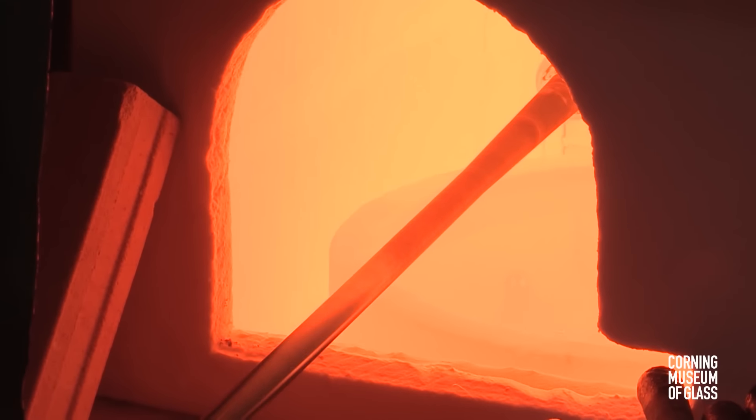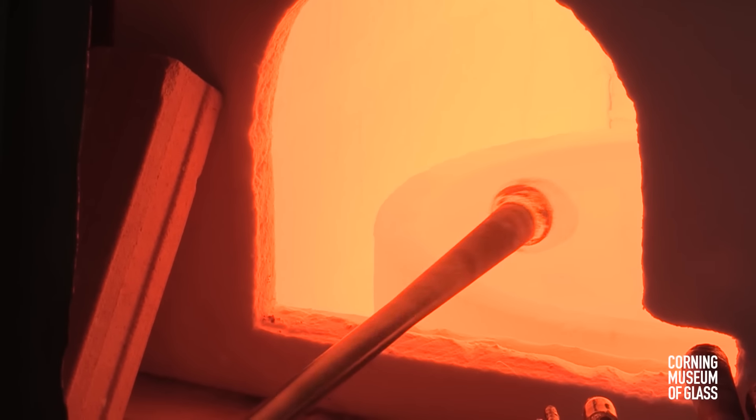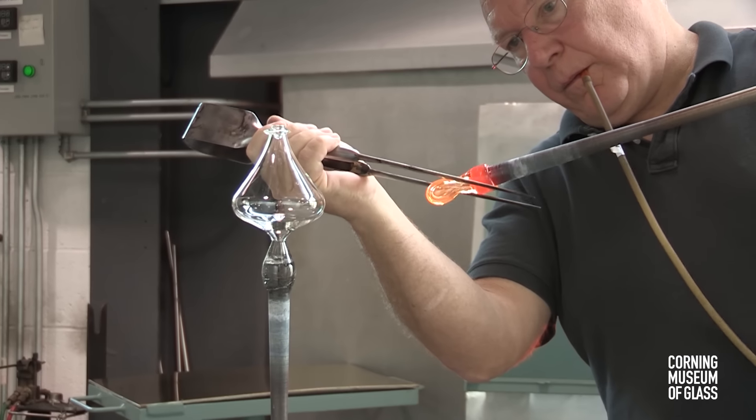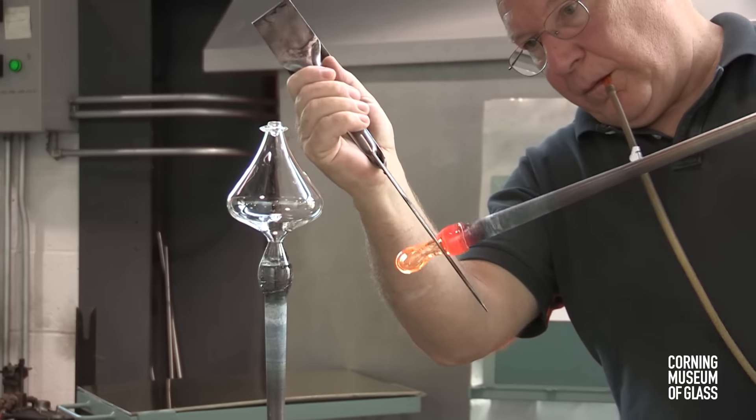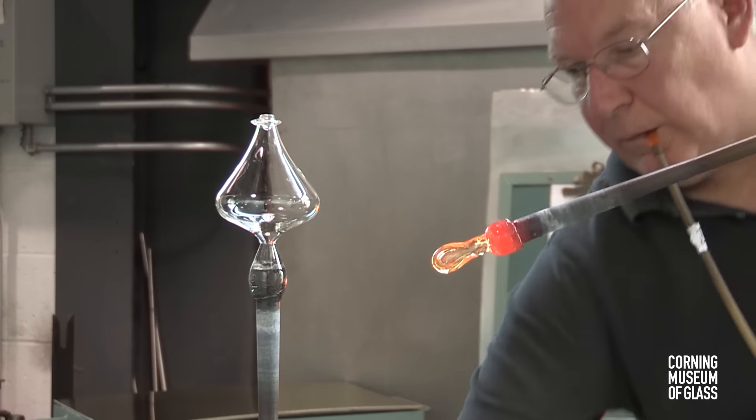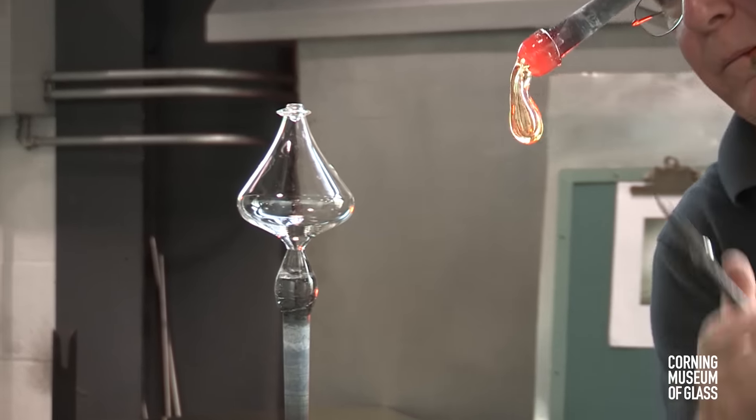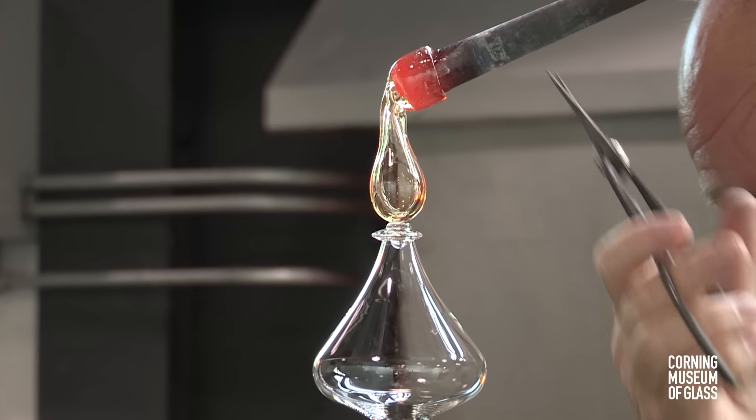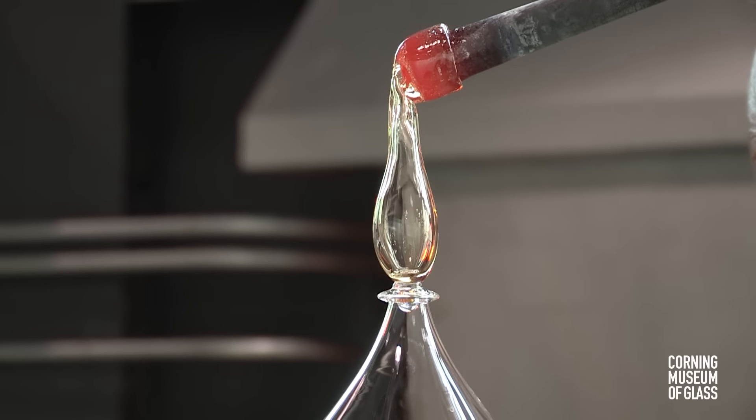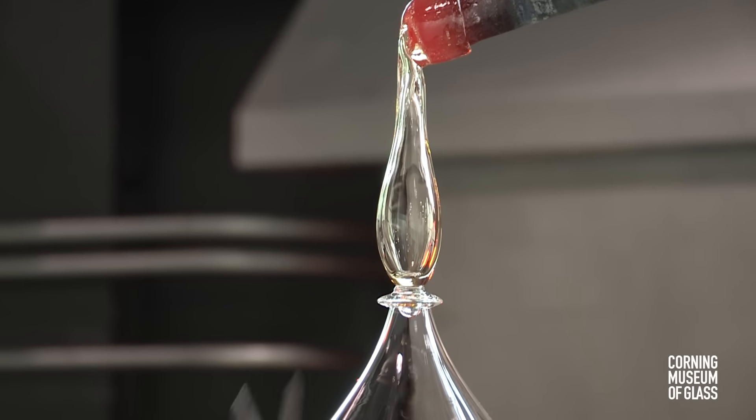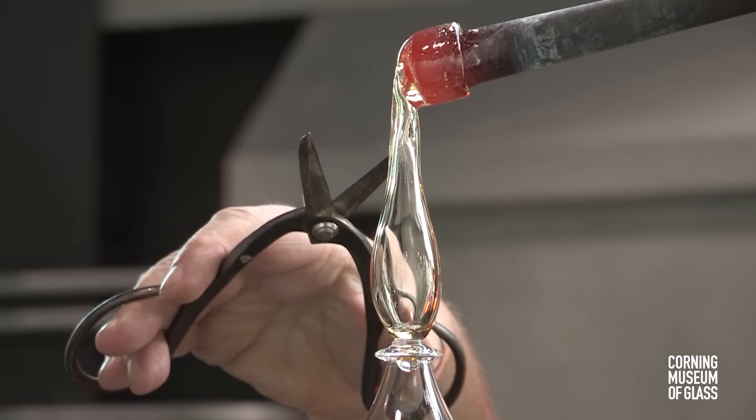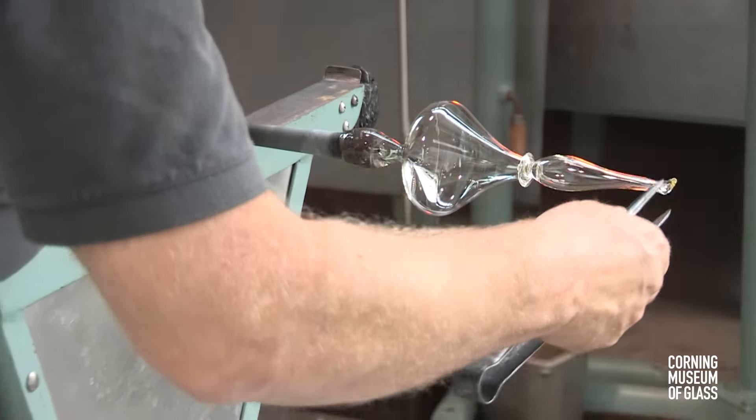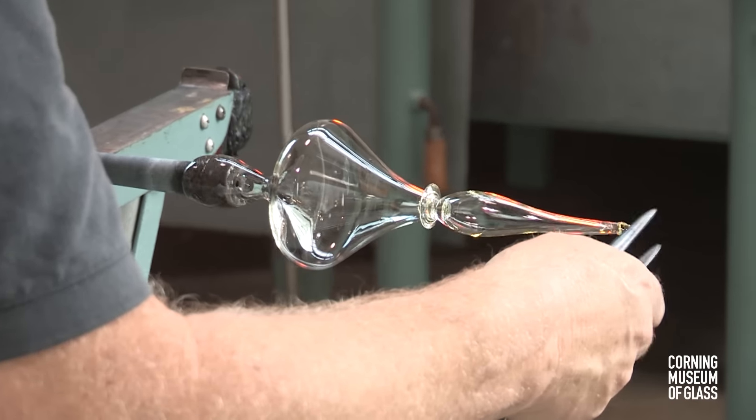Another gather of glass is made, this time a smaller one. A bubble is blown, a broad constriction is made near the blowpipe, and this will become the stem. It's lowered carefully onto the merese, inflated, pulled upward, and trimmed free of its gathering blowpipe.